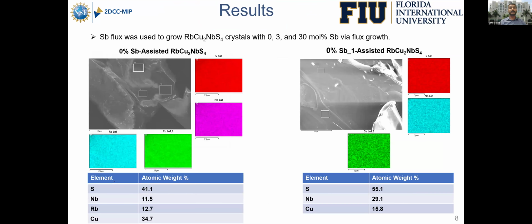Then for the flux growth, antimony flux was used to grow rubidium doped copper niobium sulfide crystals with 0, 3, and 30 mole% antimony via the flux method. Interestingly, without antimony, I labelled it as 0% antimony and 0% antimony _1. So we are able to grow 2 different types of crystal in the same batch. The 0% antimony has rubidium in it. On the other hand, the 0% antimony _1 doesn't have rubidium in it, which is kind of interesting.